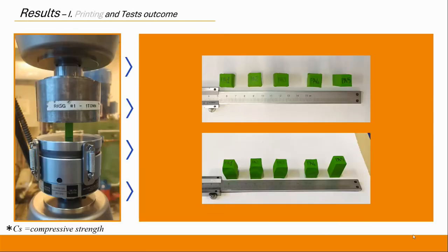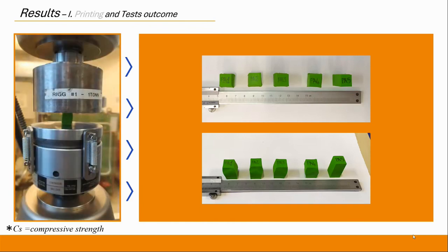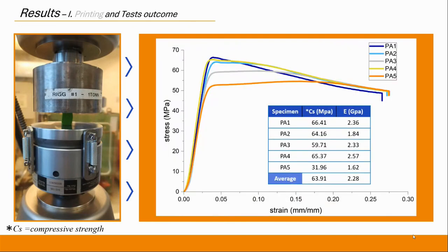As shown in the picture, all the specimens after the test have the same deformation, which developed principally after the yield stress was reached. The stress-strain curves exhibit a linear response just after the accommodation of the loading plates at the initial stages of the deformation process. We decided to exclude the last specimen from the average value analyzed since the printer showed some failure with the cooling system. The compressive strength and elastic modulus are comparable with the ones of the literature review.